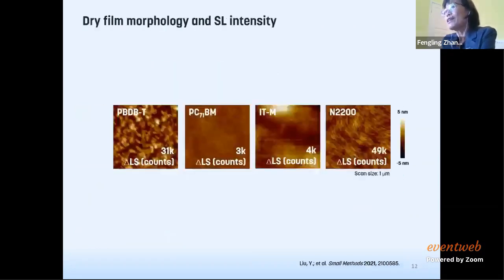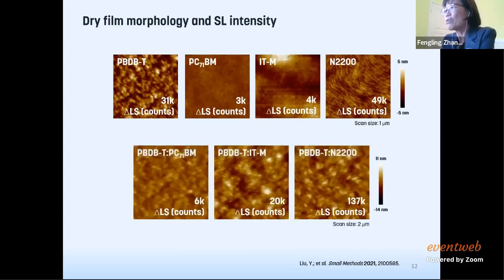So the morphology, of course, we don't know the bulk morphology. We can see the top graph. So in the top graph, the top is the pure material and the bottom is the 3 combinations. Still, you can see here, for the small molecule acceptors, it's dominated by the donor. And for the polymer acceptors, it's dominated by the acceptor. It's due to the molecular weight of the acceptor being even larger than the donor. So that's the conclusion we get from this part of the work. Larger molecular weight determines the drying process and dominates the final morphology. The top graph at least shows us this.